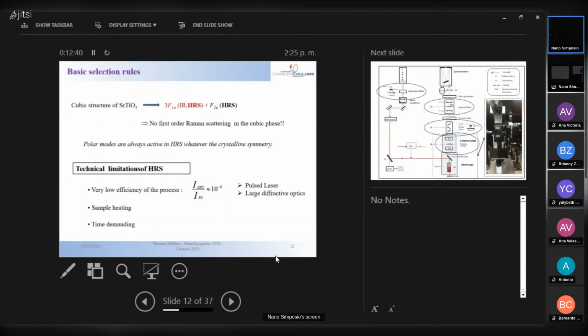For example, if you take the cubic structure of strontium titanate, you see that you have the polar modes F1U. The three polar modes are active in infrared and hyper-Raman. And there is another one, F2U, which is only active in hyper-Raman. But you see, since strontium titanate is cubic, there's no mode active in Raman. So if I want to follow this polar mode, the mode which makes this motion of the central atom moving up and down, I can't use Raman scattering. So the way to do that is to use hyper-Raman scattering.